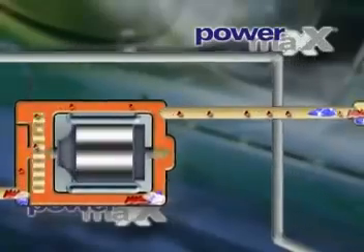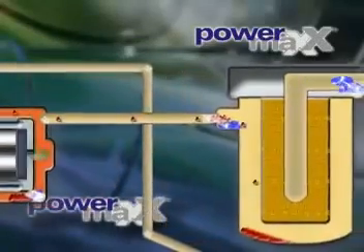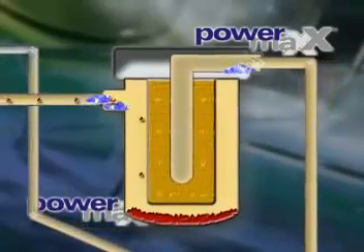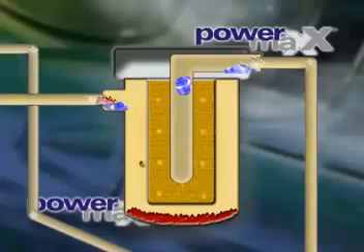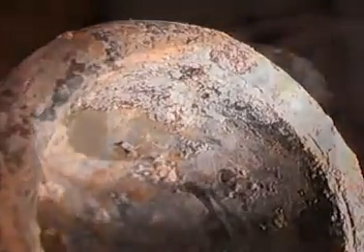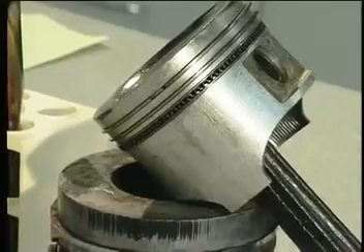This highly aggressive alcohol-water mixture then passes through the fuel filter unhindered and has a destructive effect on all the component materials downstream. Aluminium parts are particularly at risk. Aluminium hydroxide can be formed in them and is well known as a white powder. But cast metal parts, elastomers, fuel pipes and piston heads and rings are just as much at risk.